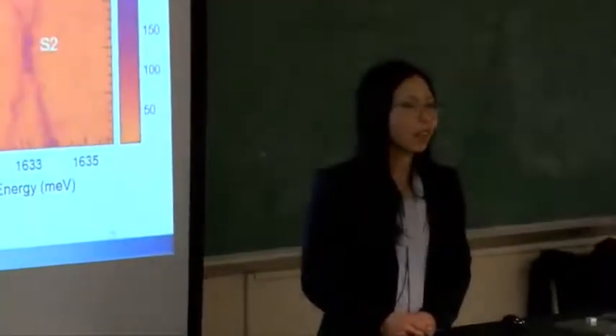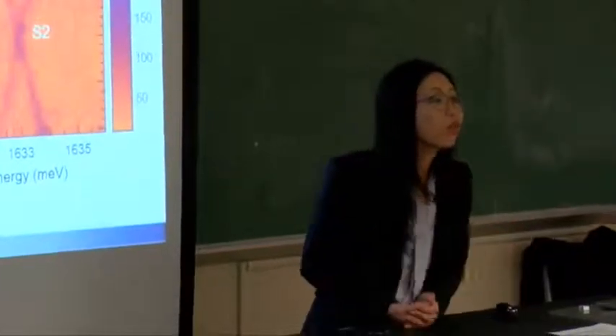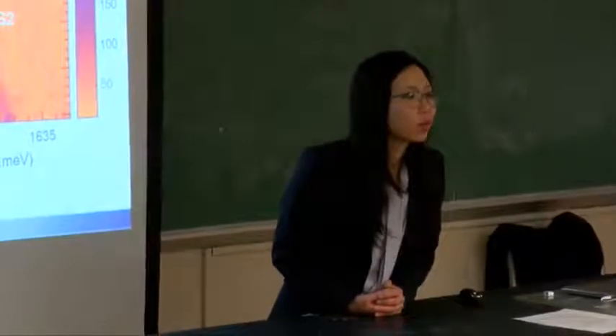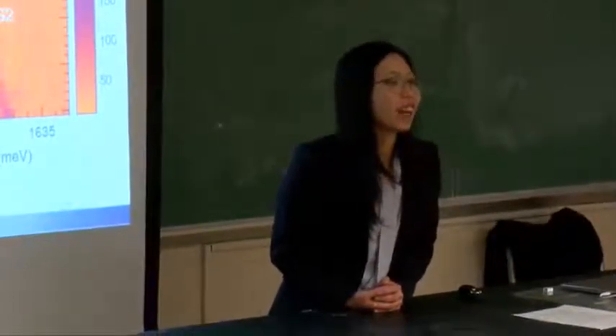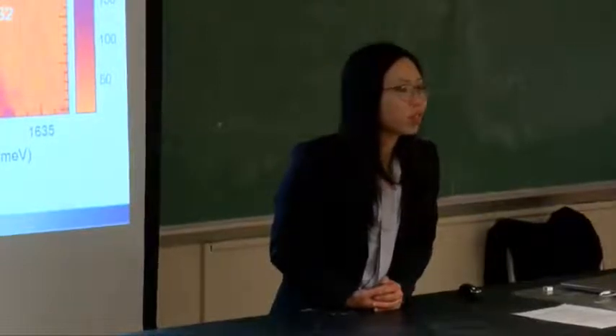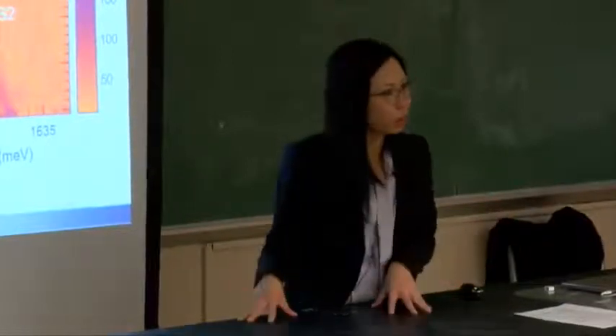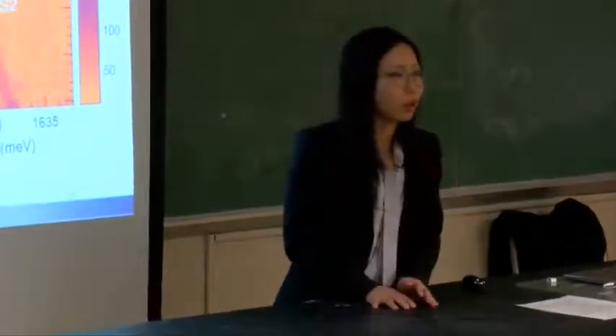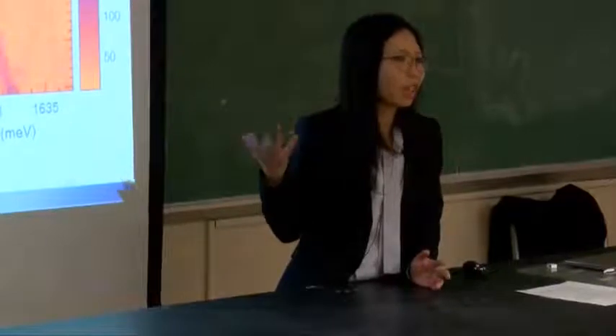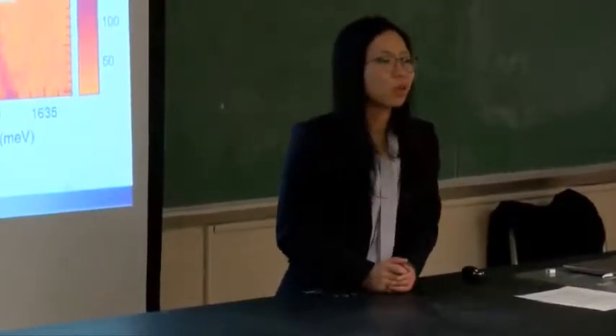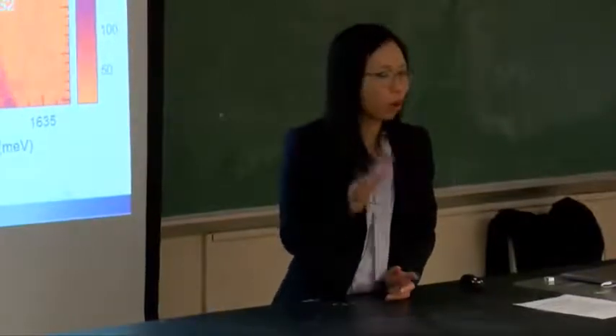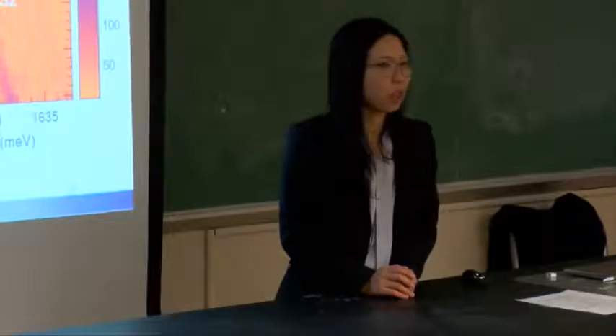I think it will affect the brightness close to zero. By brightness, you mean intensity? Emission intensity and also the G factor. You haven't tried different angles? We have done other angles. If it is close to zero or close to 60, you see bright emission, and the G factor will be different. One is close to 6, and the other is close to 15. If there's some random angle in between, let's say 30, which is not aligned, you will probably not see bright emission. The emission is very weak. That's the major difference in terms of angle. But from our experiment, there's not much difference for 1 or 2 degrees.